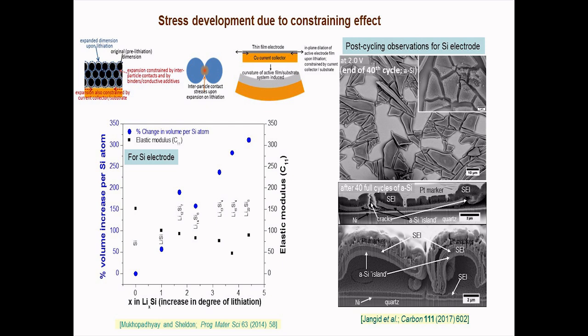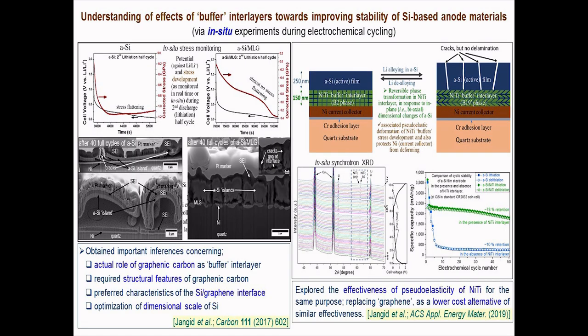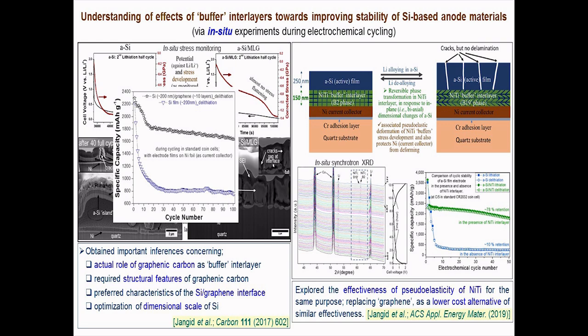The top view shows that it's totally separated, disintegrated, and the cross section view gives some funny morphology. So in order to stop this, some buffer interlayers can be used. In this case it's multi-layered graphene, again coming from Manoj's work, and compared to this without any interlayer, one can see that after the same number of cycles the electrode retains much better integrity. In fact, from this work we gained a lot of insight into why graphene as a buffer layer helps, and we figured out that it's more to do with the interface between silicon and graphene and the interface between silicon and the current collector. So one can see excellent cyclic stability in the presence of graphene as compared to without graphene.